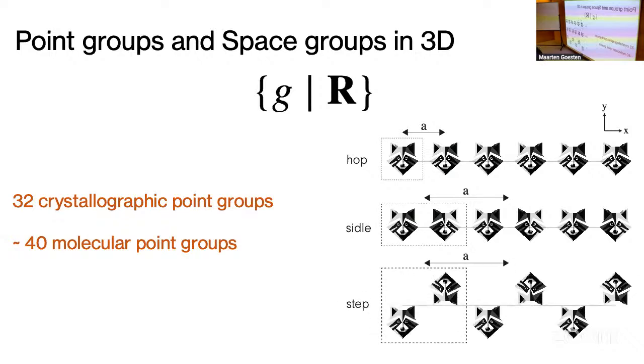Now, what we have here, and this is what is really interesting, we have non-symmorphic space groups. So this is something that has no equivalent in molecules. What you have there is you combine the linear point group operation, in this case a reflection, this is a glide plane operation. There are two types of non-symmorphic symmetry operations, screw axes and glide plane operations. So what you have here is a fractional translation combined with a symmetry operation. So this raccoon is generated from that one by a translation of a half, and then a reflection, okay? So actually, out of the 230 non-magnetic space groups, 157 are non-symmorphic. So the vast majority is non-symmorphic.